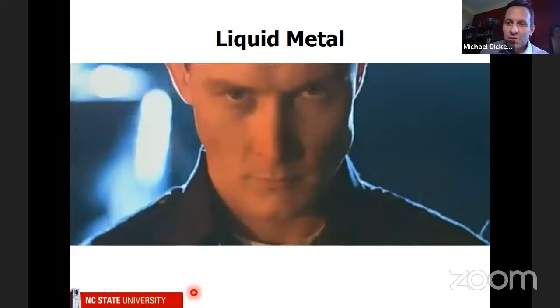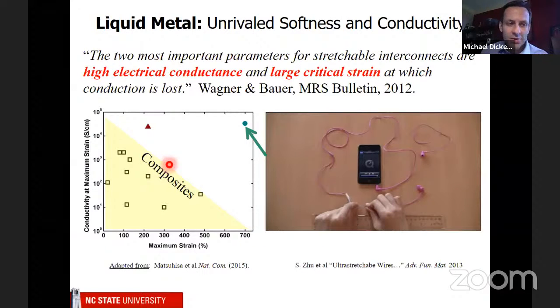To really drive home this point, I just told you that if you use a composite to make a stretchable conductor, you take a piece of rubber, and this is very, very stretchable. So on this axis, it's way over here, but it's not very conductive, so it would be down here. I can make it conductive by putting in silver or carbon particles, but when I do that, I make it less stretchable. So there's this general trade-off with composites. With liquid metal, you can make it very stretchable and very conductive.